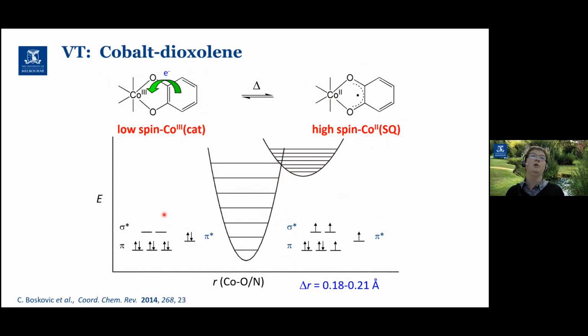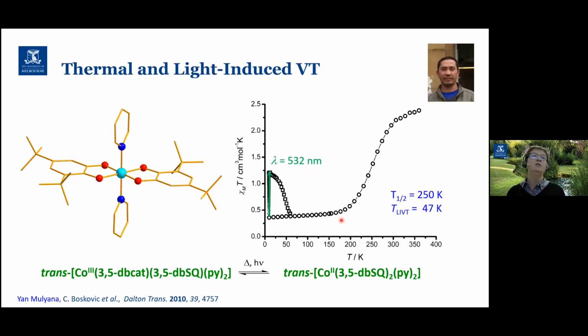Of course, as we go from low spin cobalt-3 to high spin cobalt-2, we're populating formally sigma antibonding Eg orbitals. As a consequence, all of our metal donor atom bond lengths increase by about 0.2 angstrom. So the whole molecule increases accompanying that thermal transition. Those longer bond lengths mean a higher density of vibrational states. And this thermal transition, like spin crossover, is driven entropically with both vibrational and electronic contributions. So just a really simple system.